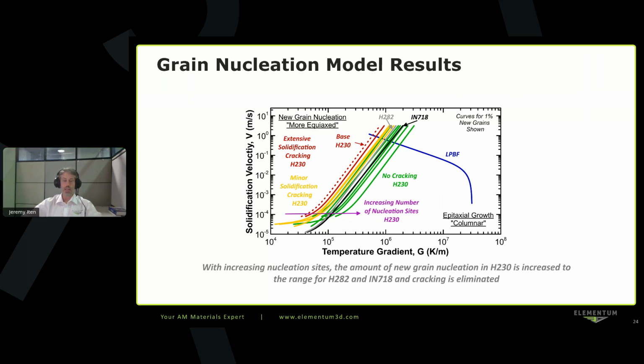We looked at a bunch of different compositions, including alloying additions, or alloying modifications, as well as adding inoculation sites. And you can see that in the green areas, we found that there was no solidification cracking with inoculation site additions through the AM processing. And in some of the cases, you're actually getting even further to the right, the columnar equiax transition, even than like an Inconel 718, which is a known friendly to print alloy.